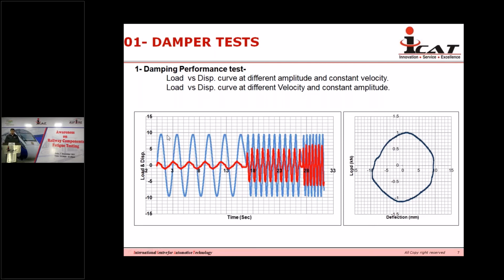This curve is for different velocities, but the amplitude is 9.5 mm. We keep the stroke at the middle: the damper has an overall stroke of 100 mm, so we keep it at 50, and then from there we give some amplitude. That amplitude is decided already by the customer, and we provide that through our servo hydraulic actuator with different frequency, or you can say velocity. One is at 0.5 hertz, then 1 hertz, then 2 hertz. The load continuously increases with respect to frequency, or higher velocity.